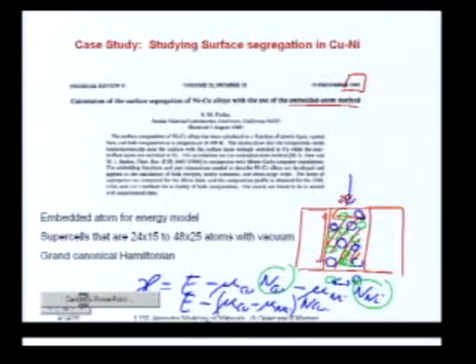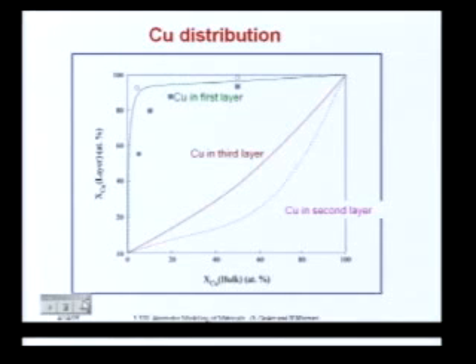You know, this was 1985. You'd be amazed how easy this is to do now. If you wanted to do something like this yourself, with a Hamiltonian-like embedded atom, it really goes very fast, and you could equilibrate systems like this in no time. But here's the result. This is as a function of the bulk concentration of copper. This is the amount of copper in the first and second and third layers. So the green curve is the first layer. So clearly copper segregates to the surface in this material.